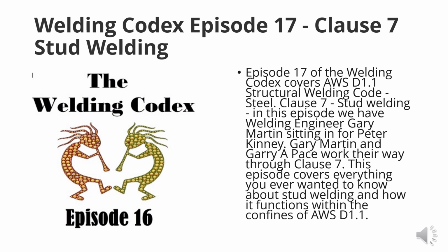And things can get a little weird here, depending on the current and what you've got going on. I don't want to use the term arc blow, but magnetically, electrically, depending on what your situation is on what you're welding, the flash from the arc can have a tendency to go in a weird direction. So you might have more on one side and less on the other if all the conditions aren't optimum. And I say this from experience. Then you have to move around welding cables and make sure you've got a better electrical and magnetic situation for the people trying to perform the work.